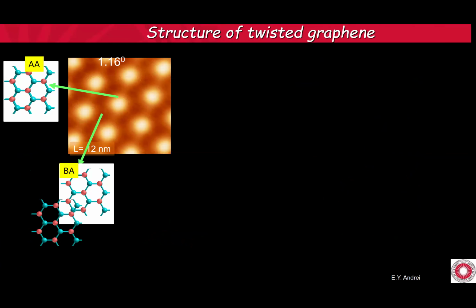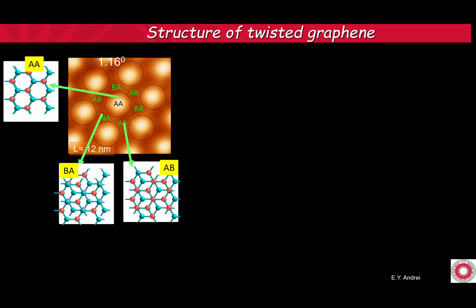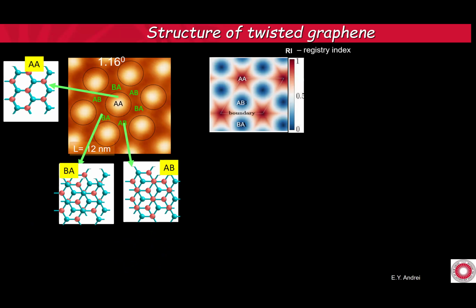Okay, so what are these bright spots that we see? The bright spots correspond to AA stacking, where every atom in the top layer has a neighbor in the bottom layer. The dark spots correspond to either BA, where a B atom is sitting on top of an A atom, and the B atom in the top layer has no neighbor, and vice versa in the AB part. So when you calculate the registry index, which is the ratio between the AA regions and the AB regions, it doesn't matter what the twist angle is. It's always the same. They always have the same area.